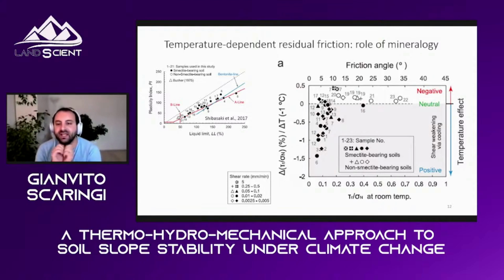Interestingly, this pattern is only valid for slow shearing, the typical slow shearing that is done in the laboratory. If the soil is sheared fast, and by fast I mean above 0.1 millimeters per minute, which in terms of landslide movement corresponds to rapid landsliding, the behavior is reversed, and smectitic clays weaken at high temperature, which is something more known in the literature for fast landslides. In fact, in our laboratory we are exploring whether on the opposite side, non-smectitic clays, for example, kaolinite, would actually strengthen at fast speed, and it seems that it is like that.